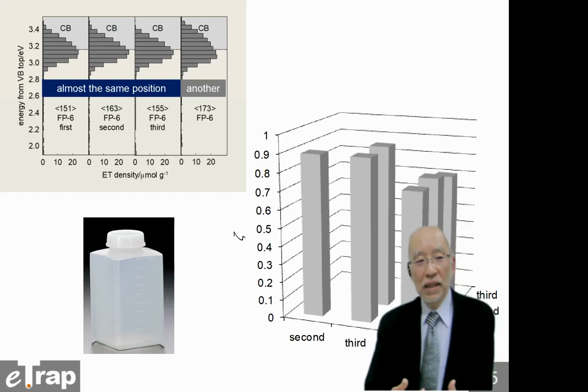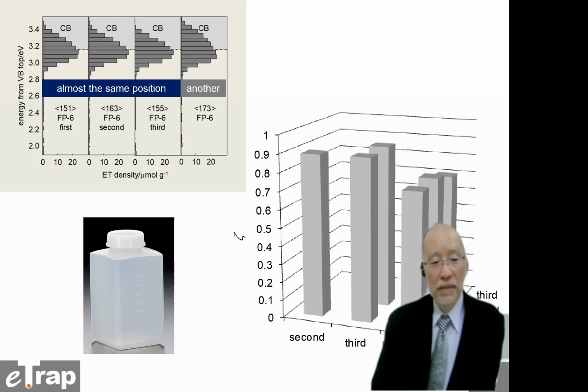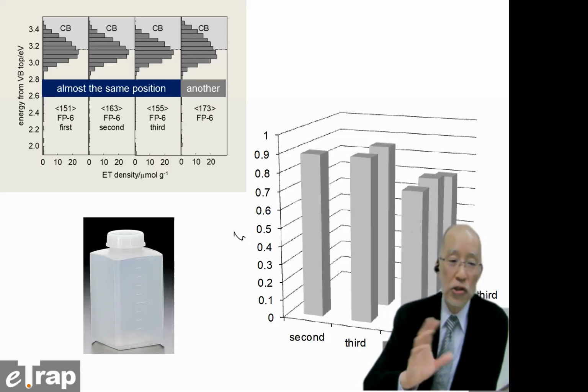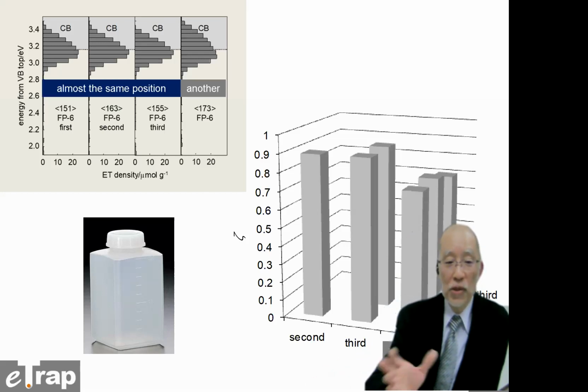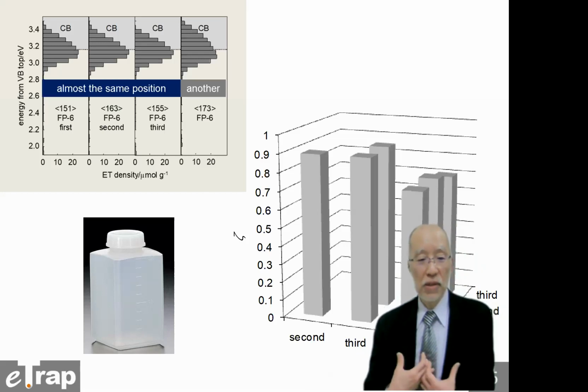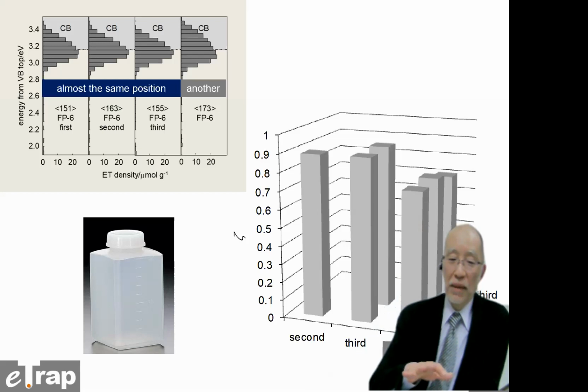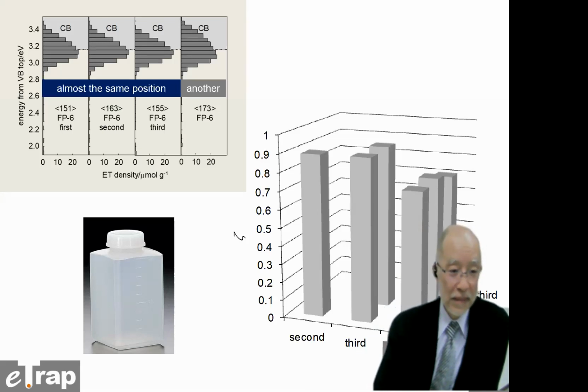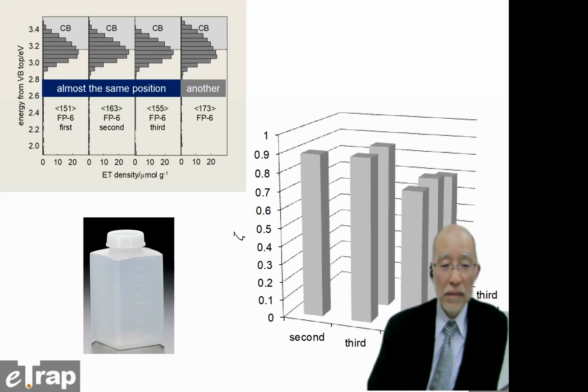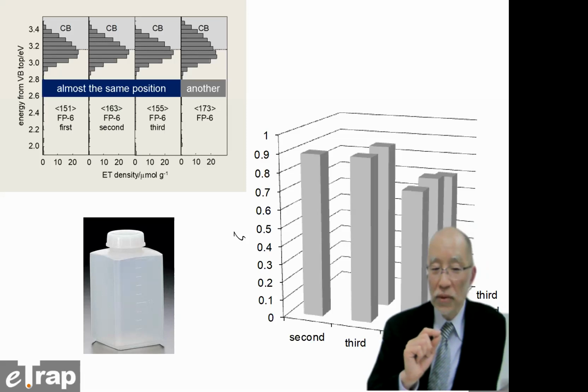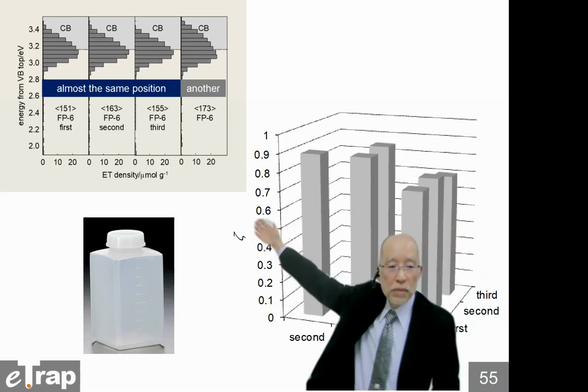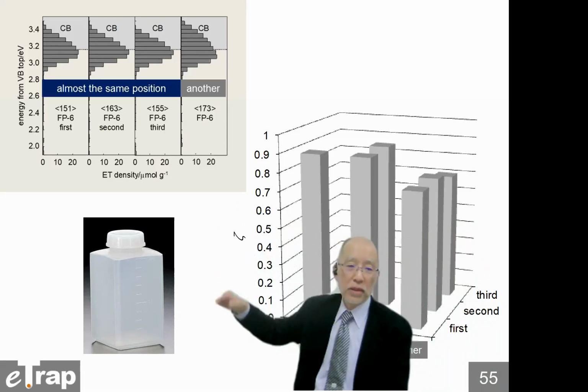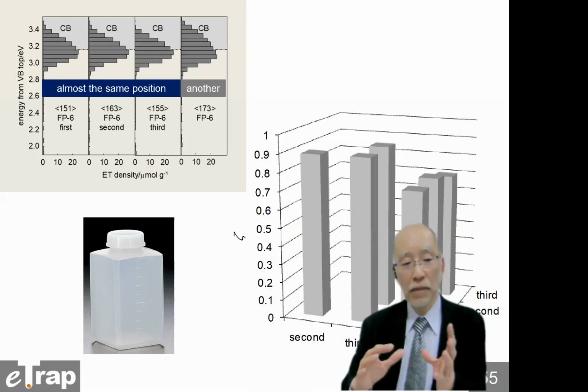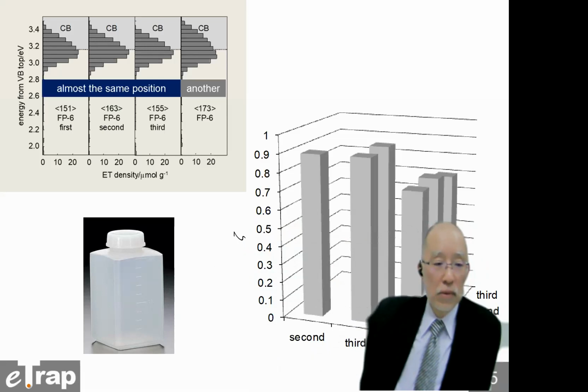So the higher density grains go down, and the lower density, lighter particles go up. So the heterogeneity must be increased by shaking. And ordinary transportation gives some shaking. And when we receive those samples, the powder has some heterogeneity. So this is important. We couldn't measure those heterogeneities in the bottle by bulk structure because it is almost the same. Probably such a difference suggests a difference in surface structure. Even if the particle size and bulk structure are almost the same, if the surface is different, we can detect those differences.